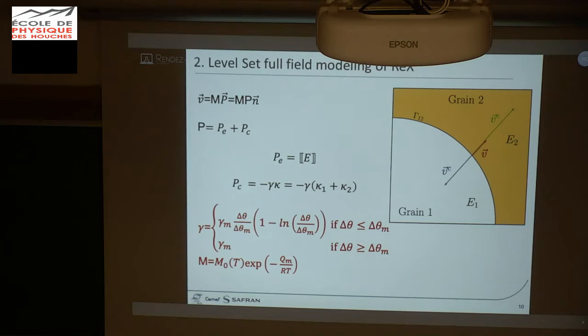And we can see that what we classically use is two driving pressures, one of which is due to the energy stored during deformation. Don't forget that we will speak about thermomechanical processing, and that we can have large deformation of materials, and of course we are going to store dislocations during deformation, and these dislocations are responsible for intragranular stored energy. The idea is to be able to take into account this driving pressure to simulate dynamic, metadynamic and static recrystallization phenomena.